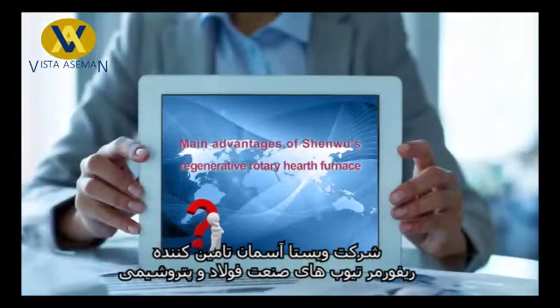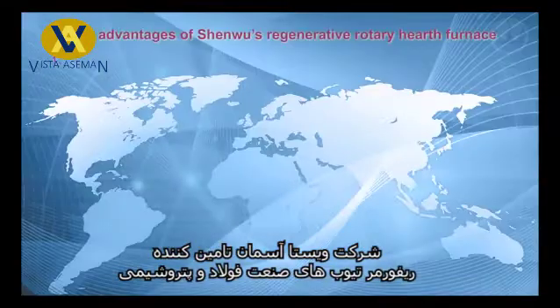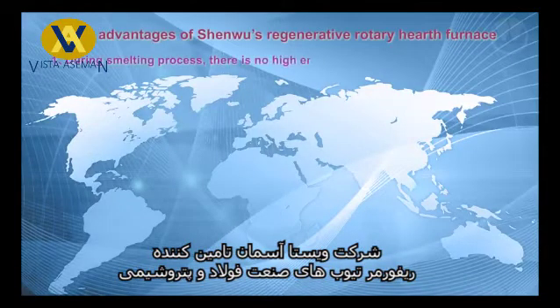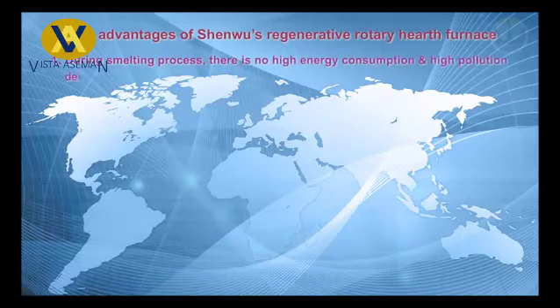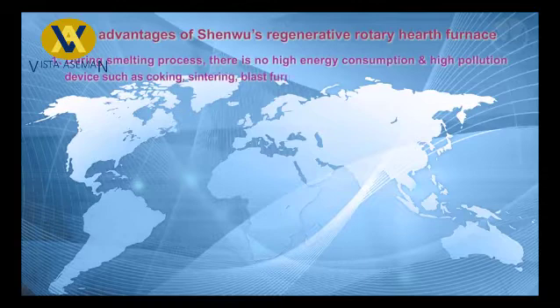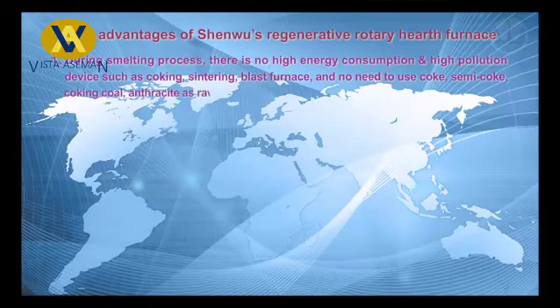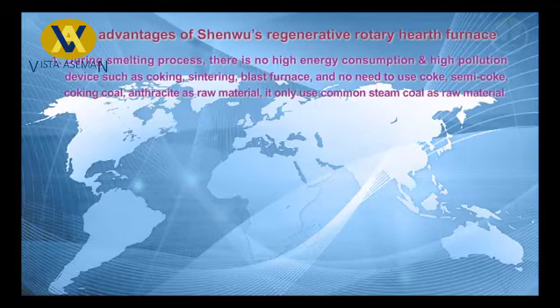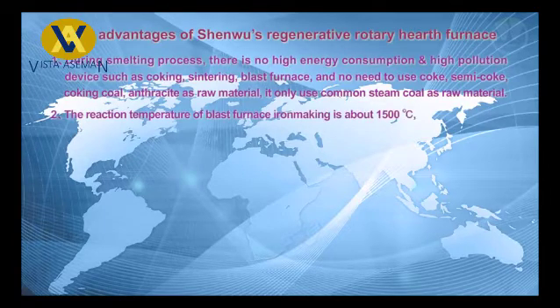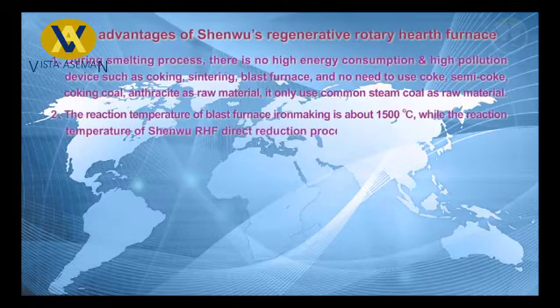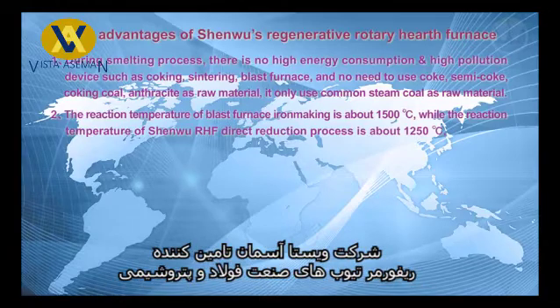Main advantages of Shenwu's regenerative rotary hearth furnace. 1. During the smelting process, there is no high energy consumption and high pollution device such as coking, sintering, blast furnace, and no need to use coke, semi-coke, coking coal, anthracite as raw material. It only uses common steam coal as raw material. 2. The reaction temperature of blast furnace iron making is about 1500 degrees centigrade, while the reaction temperature of Shenwu RHF direct reduction process is about 1250 degrees centigrade. The energy consumption is therefore significantly reduced.